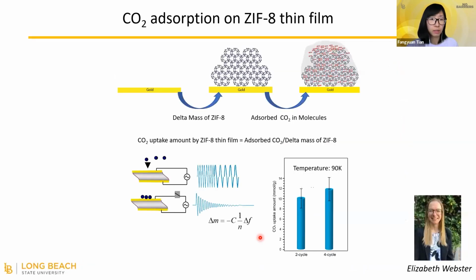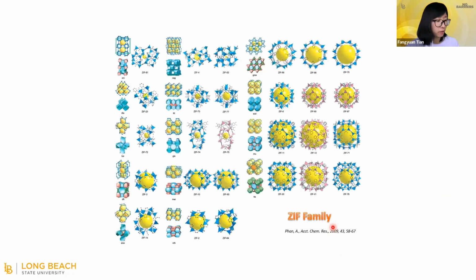But when we look at the carbon dioxide absorption amount, we found that ZIF-8 can absorb lots of carbon dioxide, around 10 millimole per gram of ZIF-8. But for this type of carbon dioxide trapping, we have to do this measurement at 90 Kelvin. That means this material is only effective for trapping carbon dioxide at extremely low temperature. But for landfill and petroleum or natural gas systems, we usually handle those gases around room temperature. So this is not very practical.